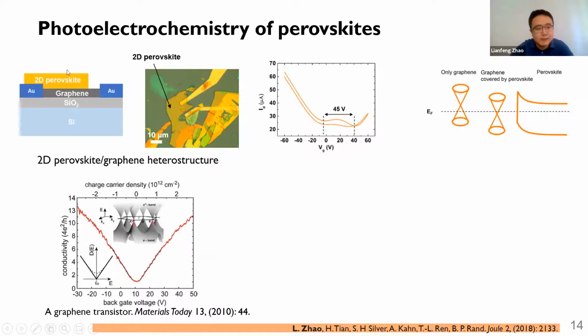This is because we only covered half of the graphene channel with perovskite, and the interaction between perovskite and graphene shifted the Fermi level of graphene for this part. So one current minimum corresponds to the graphene channel that is not covered by perovskite, and the other current minimum corresponds to the graphene channel that is covered by perovskite.